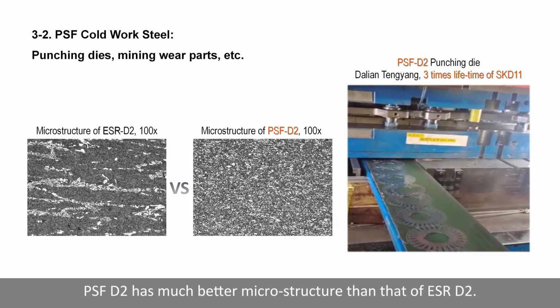PSF D2 has much better microstructure than that of ESR D2. Its impact toughness is doubled, even tripled at the same hardness, HRC 60. Lifetime is improved about 3 times.